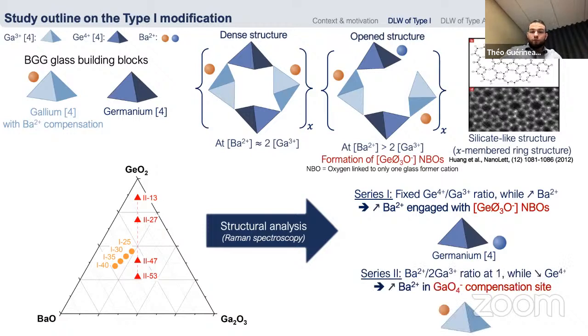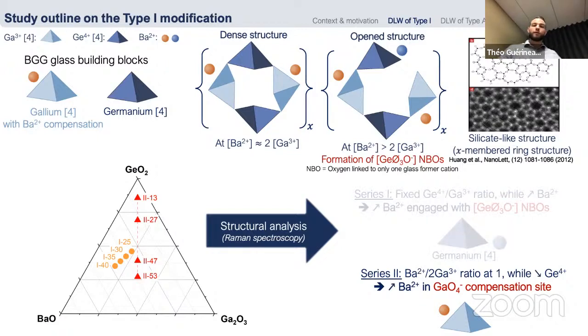But in series number 2, when we keep constant the ratio at 1 between the barium and 2 times the concentration of gallium, while we decrease the concentration of germanium, we observe an increase of the barium engaged in the compensation site of the gallium tetrahedra site. And so for this presentation, I will only focus on this series.